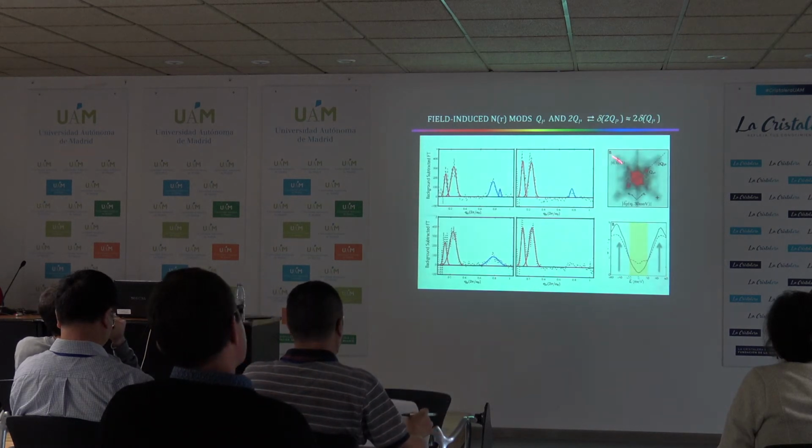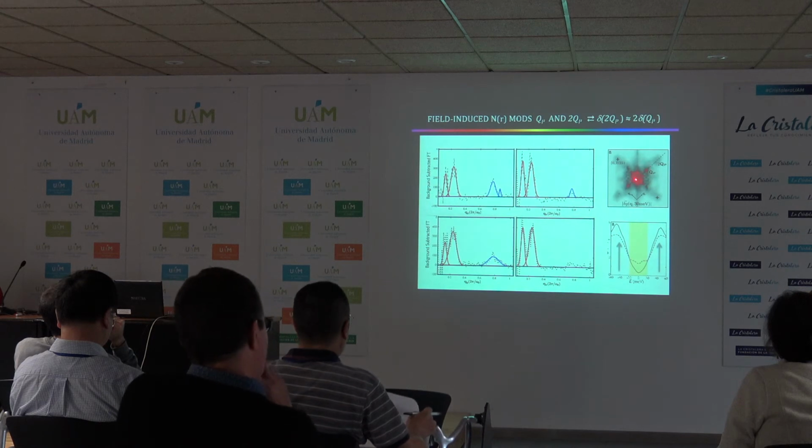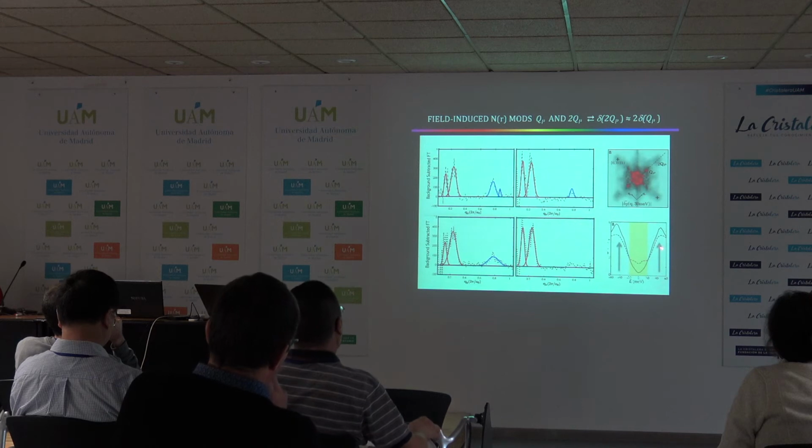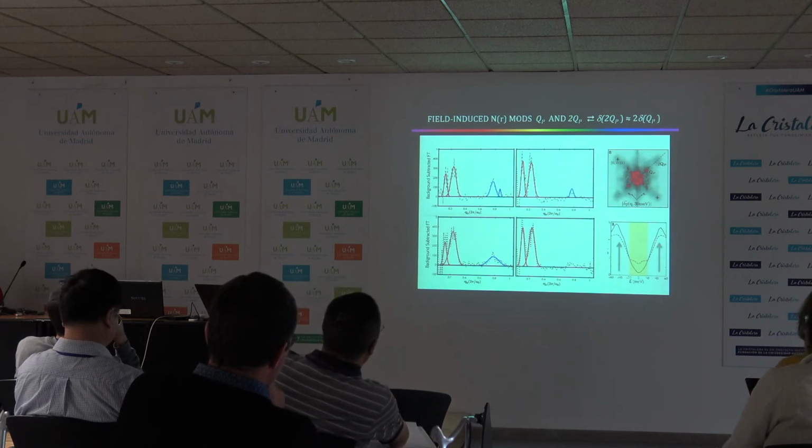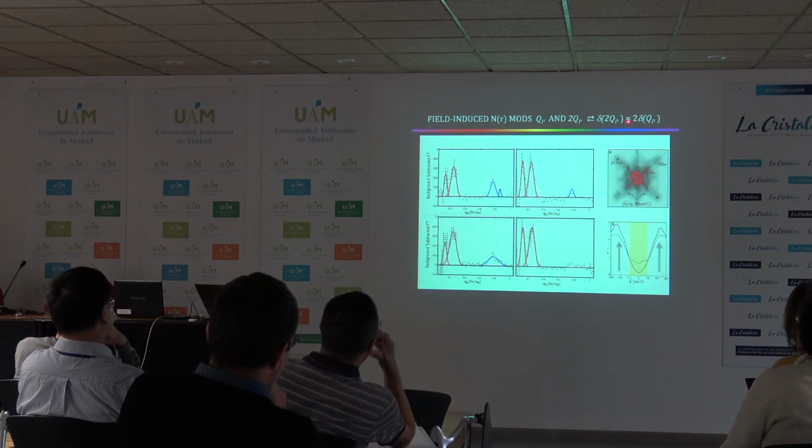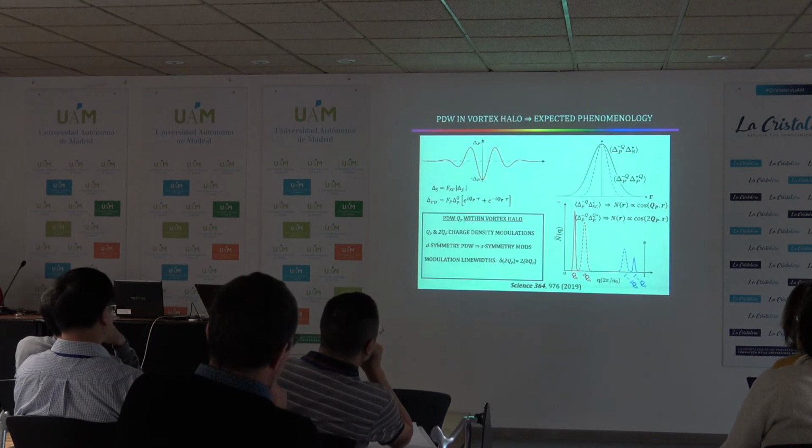Also, we actually have a good deal of information about the line widths, because we have the line width in this direction, the line width in that direction, and we have them for the two gap edges. So we have 4 pieces of information. They show quite clearly that the line width of the 2Q peak is twice the line width of the 1Q peak, with very good fidelity.